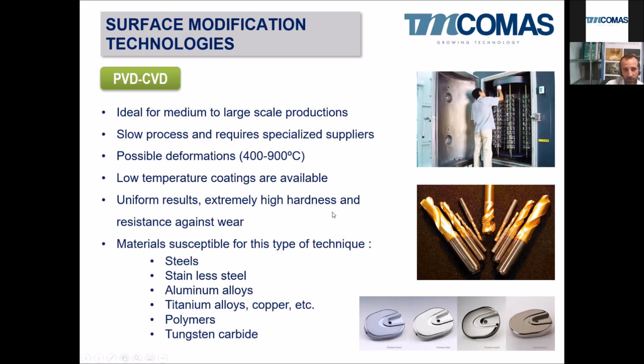Well, we are using these coatings for all the cutting tools. This is a standard procedure to coat tungsten carbide or high-speed steel cutting tools by PVD coatings. And what kind of materials are prone to this surface technology? Steels, stainless steels, aluminum, titanium, polymers. Right now we have a lot of automotive parts that are not metallic anymore, but polymeric, and with a PVD coating on top, giving you a metallic appearance like these pictures. And overall, tungsten carbide. Tungsten carbide is, I would say, the king of the base material for PVD coatings, because these are very, very big production in cutting tools these days.